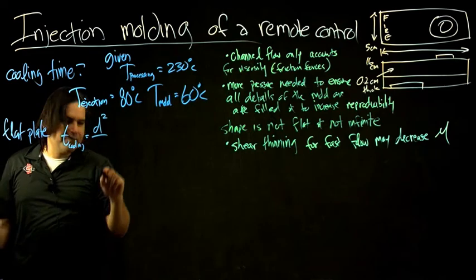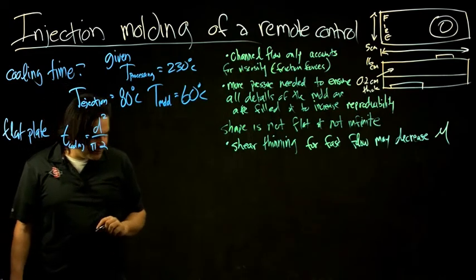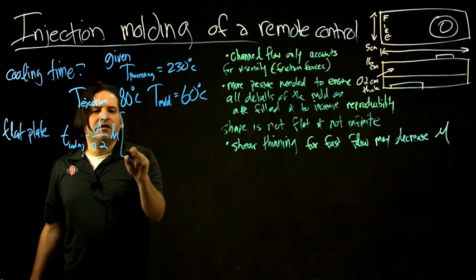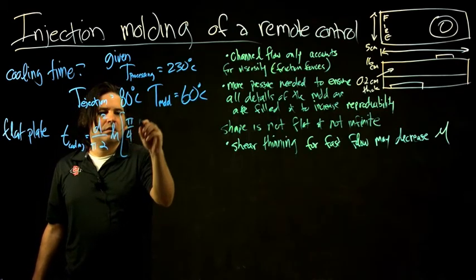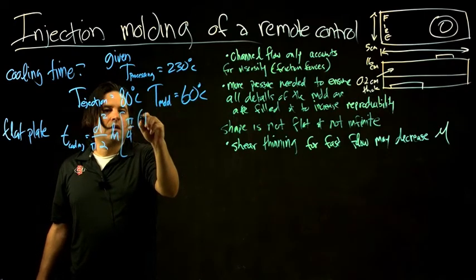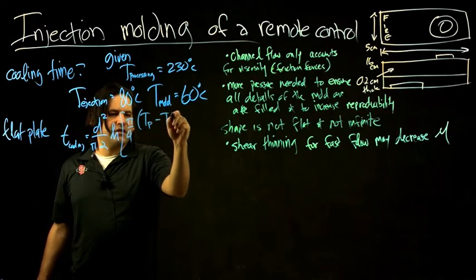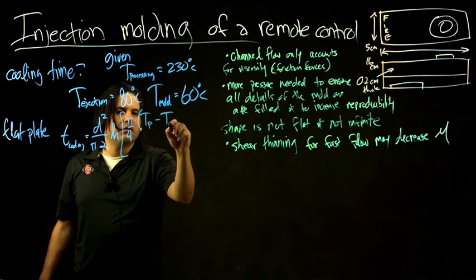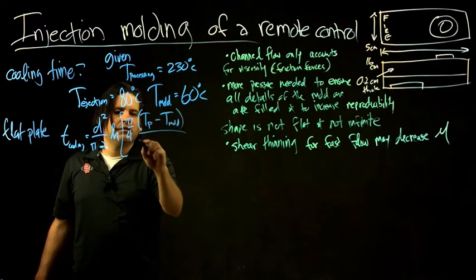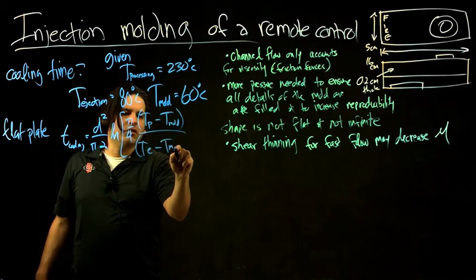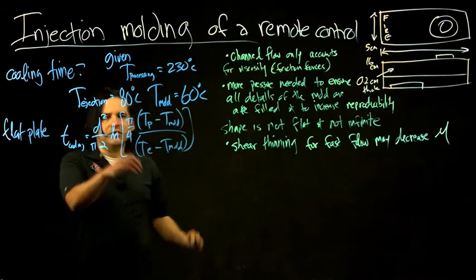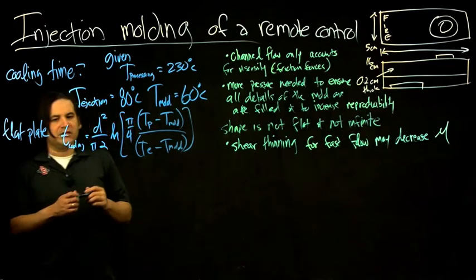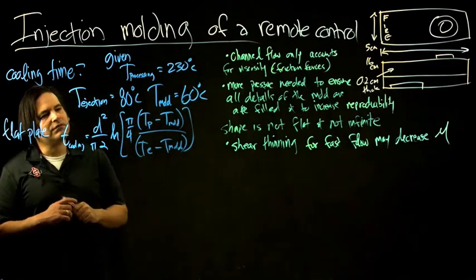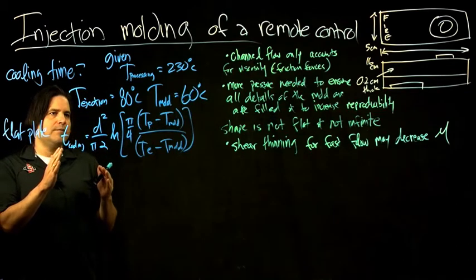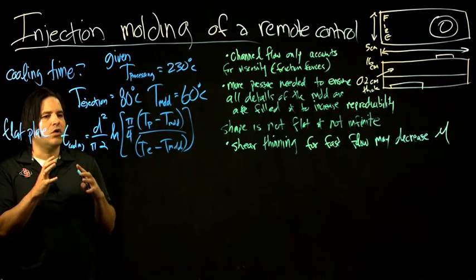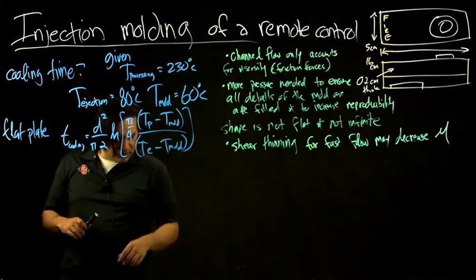The thickness of the plate, divided by pi squared, times the natural log of this T processing minus the temperature of the mold, they call it TD, over the ejection temperature minus the temperature of the mold. So that ratio is inside the natural log. That would be the solution to the energy equation. And in this case, the material has a low thermal conductivity. Oh, this is not 2, this is alpha, yeah.